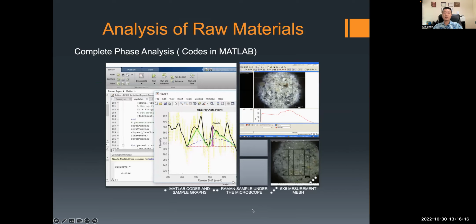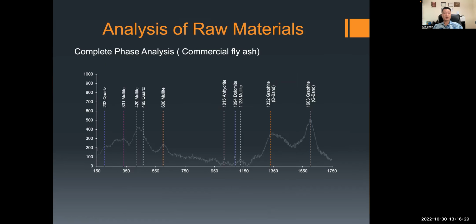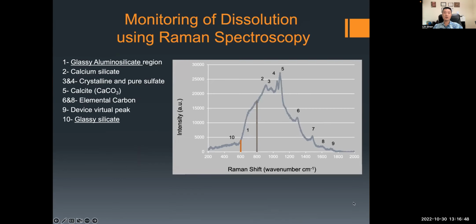We also use MATLAB codes to quickly detect and also quantify the crystal phase and also amorphous bandwidth. And here shows complete phase analysis of commercial fly ash. We can see different types of phases using Raman. So the most interesting function of Raman is its ability to monitor the dissolution process of different phases from the very beginning. So for example, here shows different phases. Region 1 here is glassy aluminum silicate, which we want to study closely. Also, phase 10, which is here, shows glassy silicate.